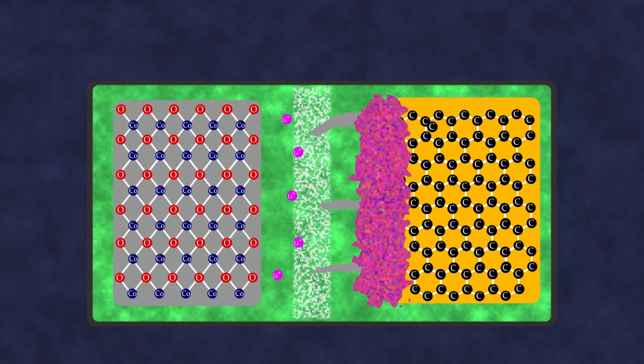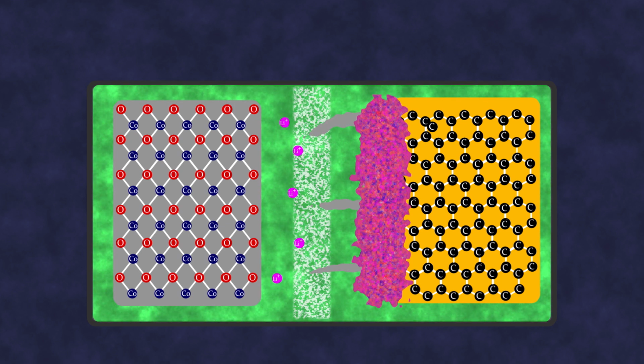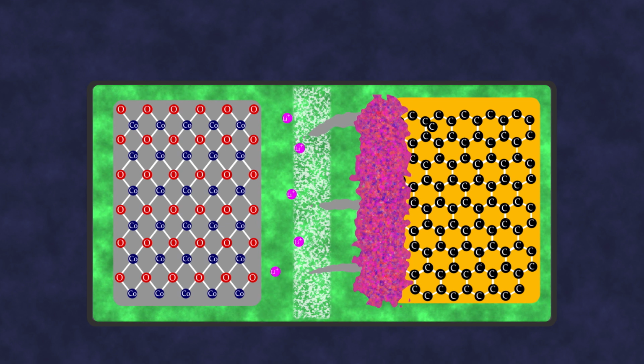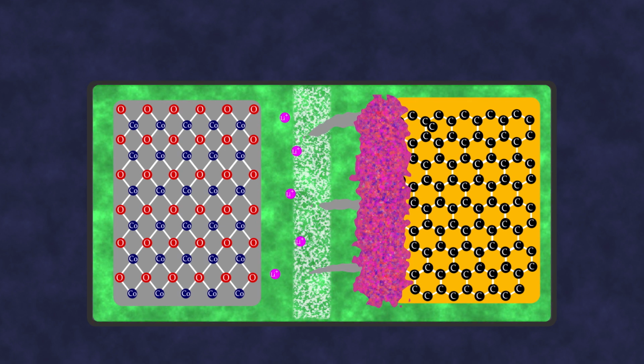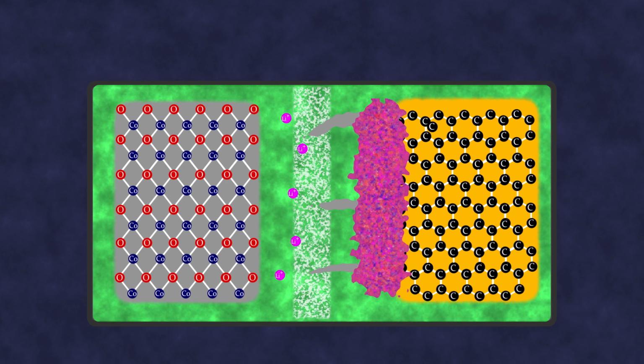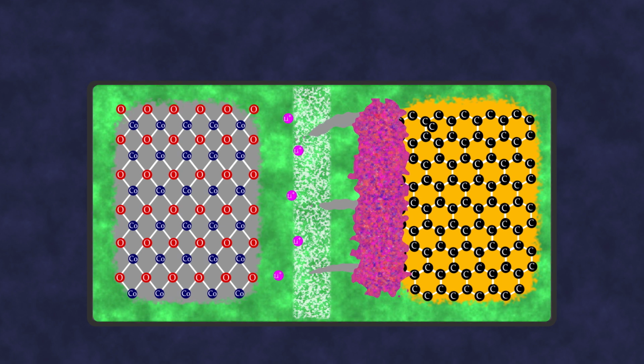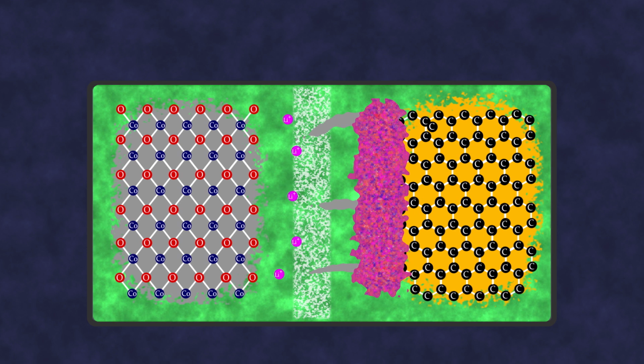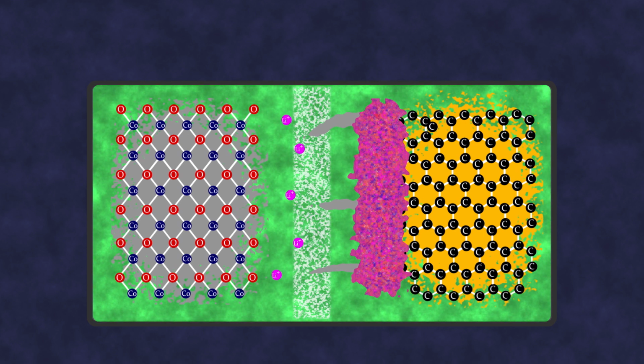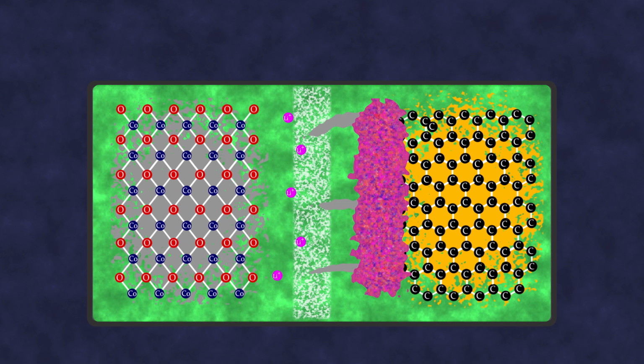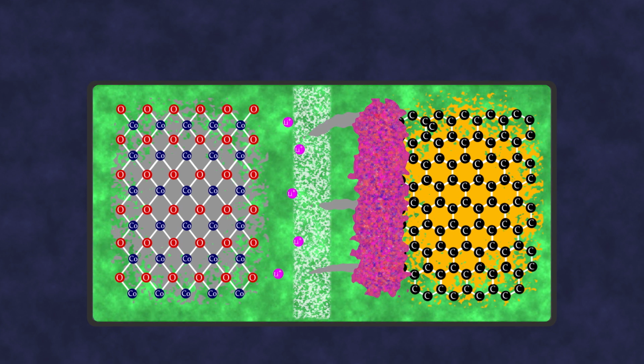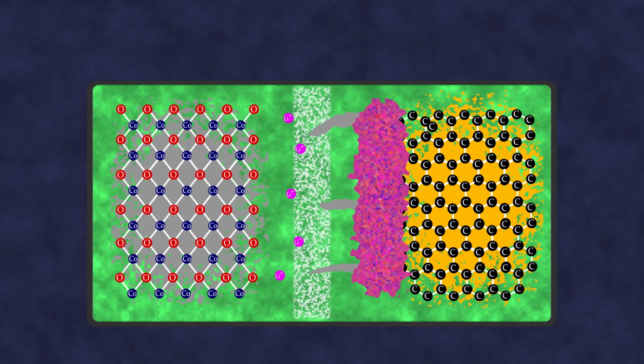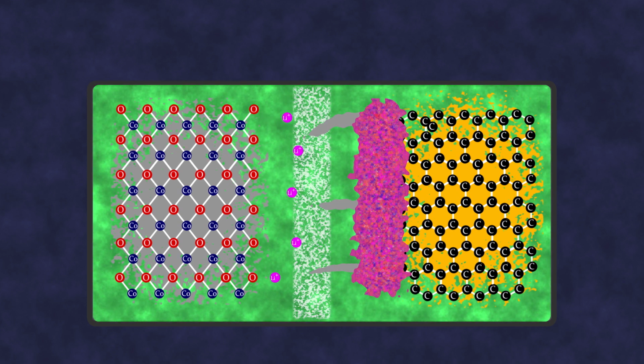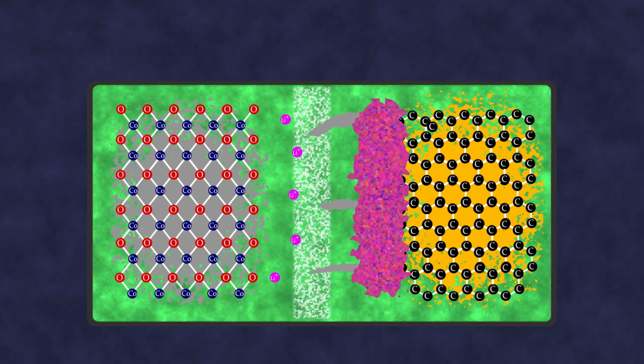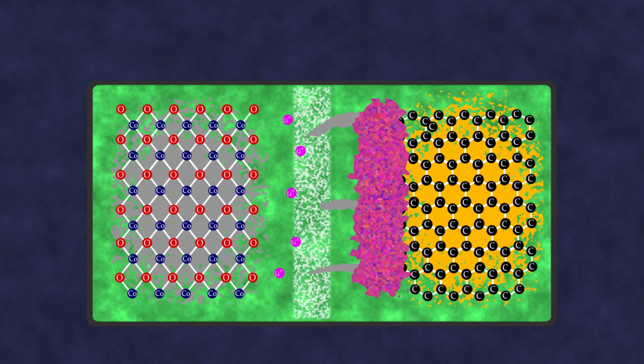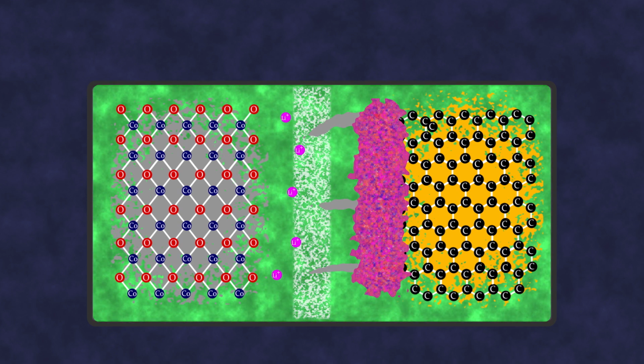It's worth noting that dendrite formation is most active when the battery is charged at low temperatures and during fast charging with high voltage. The electrolyte also interacts with the metal of the current collectors and the cathode, gradually dissolving them over time. The dissolved particles contaminate the electrolyte, further reducing its permeability and forming metallic dendrites. Moreover, the gradual dissolution of the current collectors leads to poor contact between them and the cathode and anode, again increasing resistance and operational temperature.